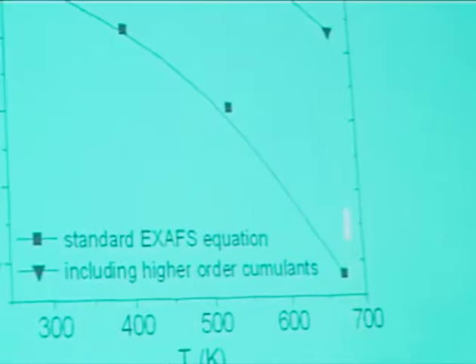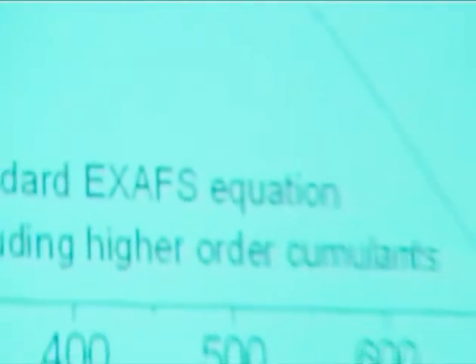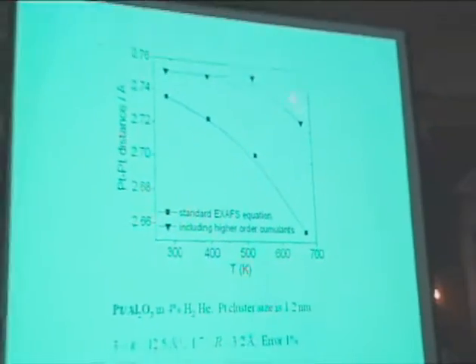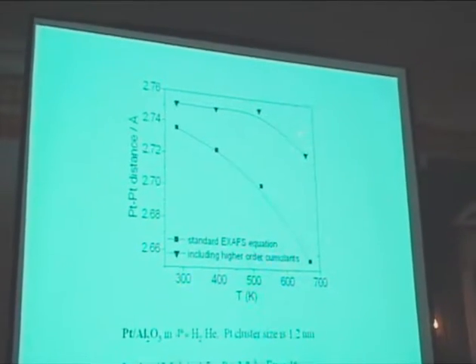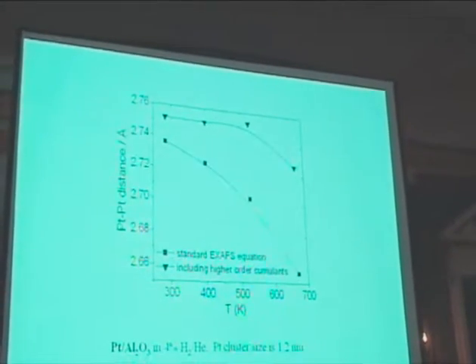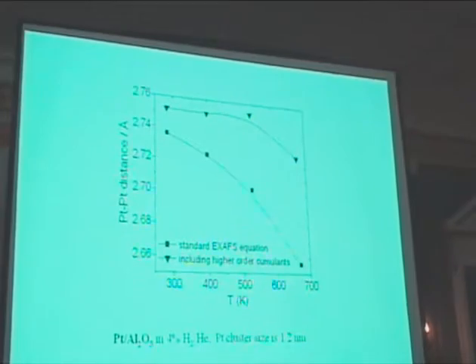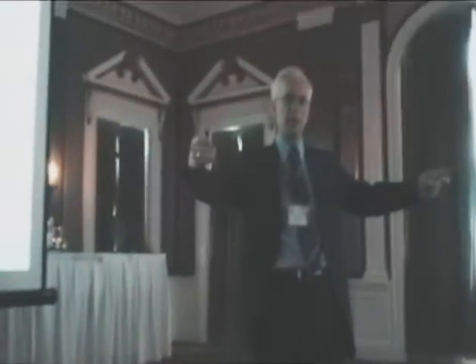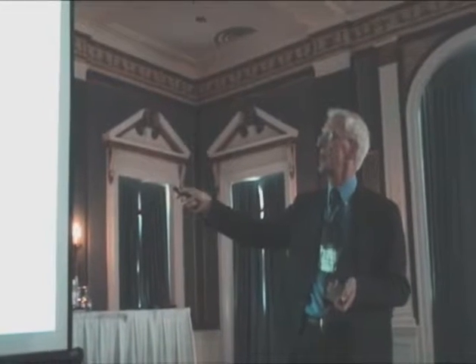Why this point? Well, by this time we are at 400 Celsius. We have now removed the hydrogen, because this was a platinum on alumina measured under hydrogen, and now we are at 400, so the hydrogen is removed, and now we contract. It's known that when the hydrogen is at the surface you expand a little bit, and when it's in vacuum you contract. So this is the contraction, and has nothing to do with yes or no cumulants.